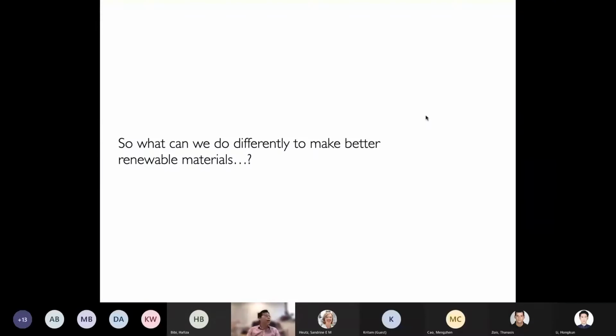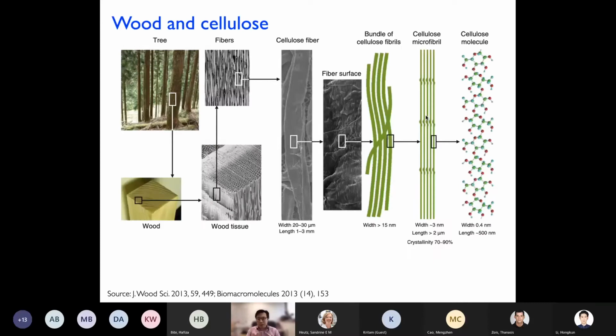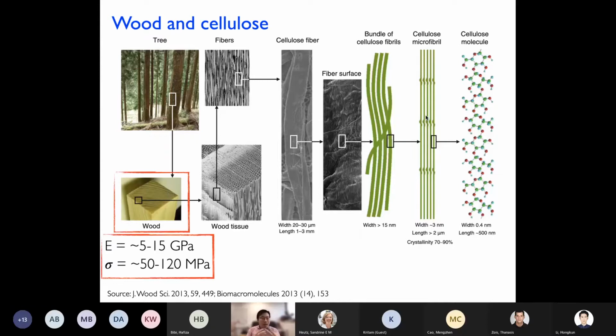If it already exists, so what can we do differently to make better renewable materials? This is where the nano aspect comes into play. So let's look a little bit at wood and cellulose. So you have trees, so we go from the top left-hand side corner there. You have trees which you debark the skin, and you get wood. And wood typically has a performance of about 5 to 15 gigapascal, strength of 50 to 120 megapascal. Not extremely exciting, but it's good enough to be used as construction materials.